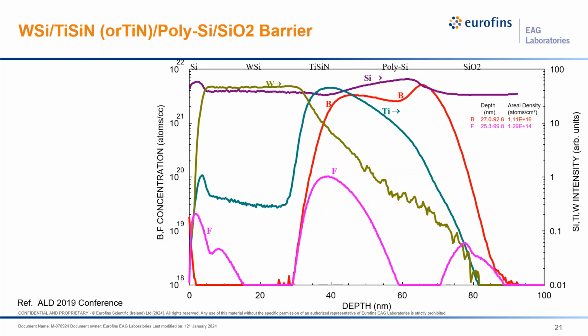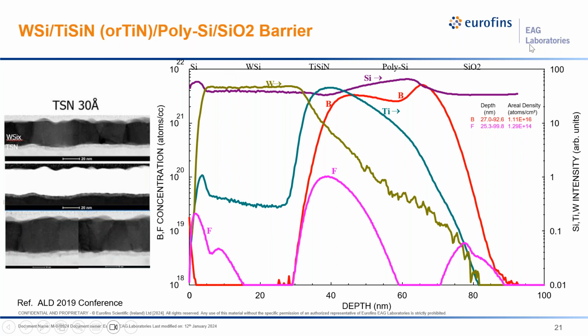So an example of the depth profile is shown here, and this is an overlay of a variety of modes. We can see here the physical structure shown in this TEM image of our sample on the left. We can see the fluorine peaks. The fluorine itself seems to have not really penetrated tremendously into the underlying material, and the boron itself certainly has not gone into the top tungsten silicide. So either way, it is important to be able to track where these elements are.